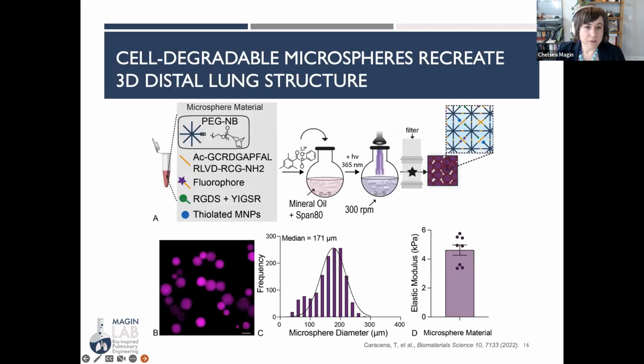So the first thing we do to make three-dimensional models of lung is to create a template for making that 3D structure that I showed you. We create cell-degradable microspheres to recreate 3D distal lung structure. These microspheres are made out of polyethylene glycol. This is a hydrophilic material that absorbs quite a bit of water, and we're able to tune the stiffness of this material to match your lungs. We include a crosslinker that's degradable by enzymes that the cells make. We add in a fluorophore so that we can see it under the microscope. And then we add in short peptides, including RGD and YIGSR. These mimic the proteins in the lungs, fibronectin and laminin, and it helps the cells stick to the microspheres.